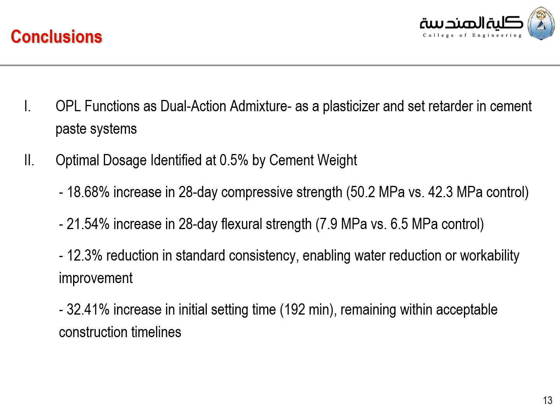It also shows a 12.3% reduction in standard consistency, enabling water reduction or workability improvement. This is very good. And it shows a 32.41% increase in initial setting time, remaining within an acceptable construction timeline.